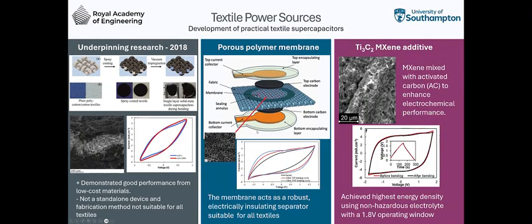And again, this works very well, has a similar sort of cycling stability, and is very mechanically robust. So that just shows after we can bend, twist, mechanically deform the device, and it still works very well. We've done a lot of things to try and improve the supercapacitor performance, such as adding MXene materials, for example, and that does have a significant improvement. So that reduces the internal resistance of the carbon electrodes, just by adding a very small percentage of MXene to the supercapacitor.